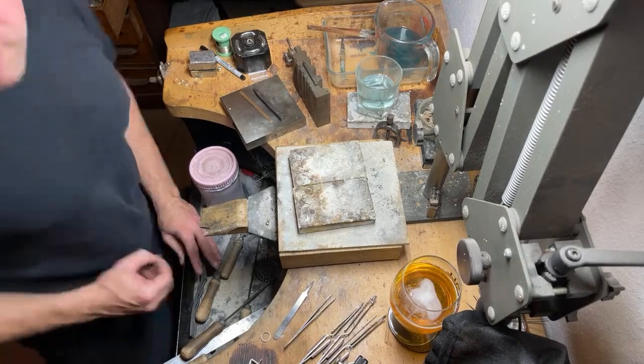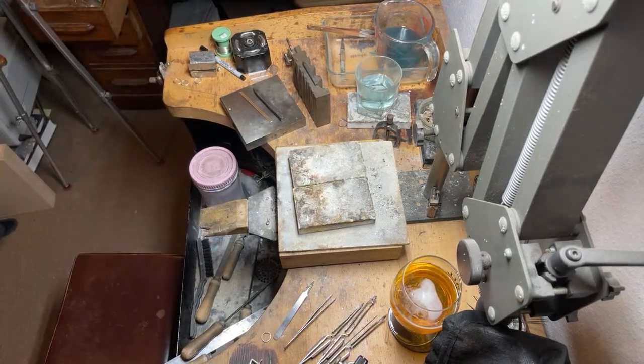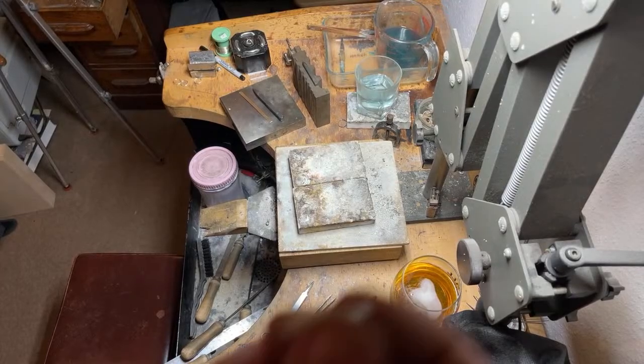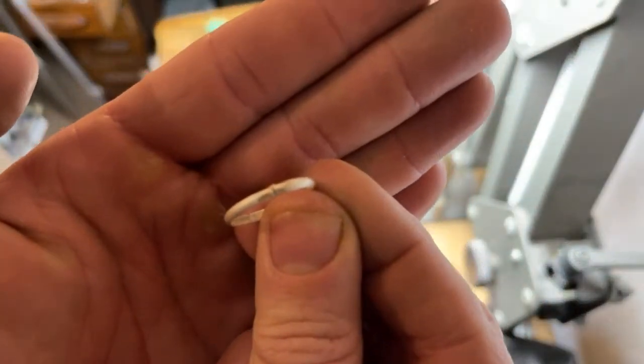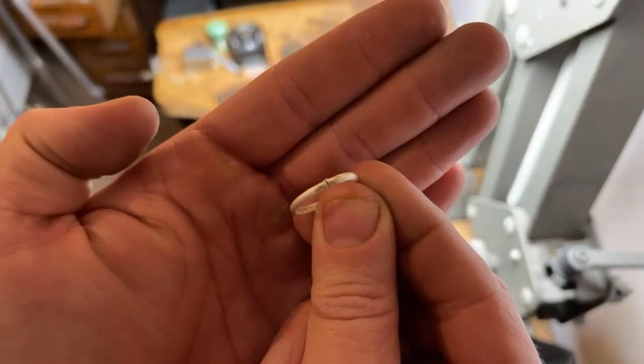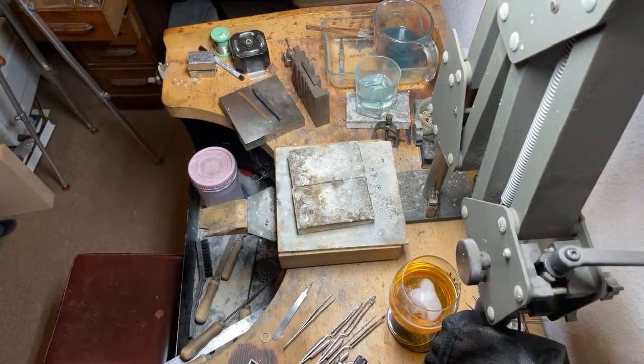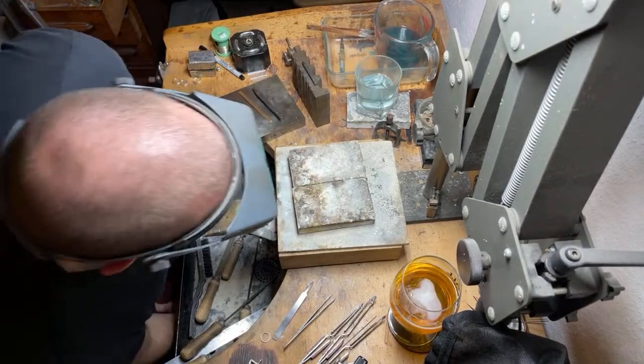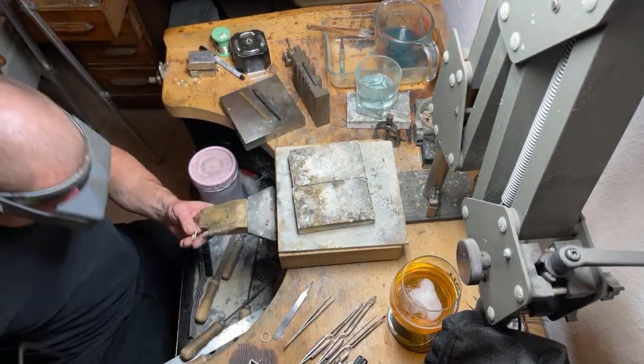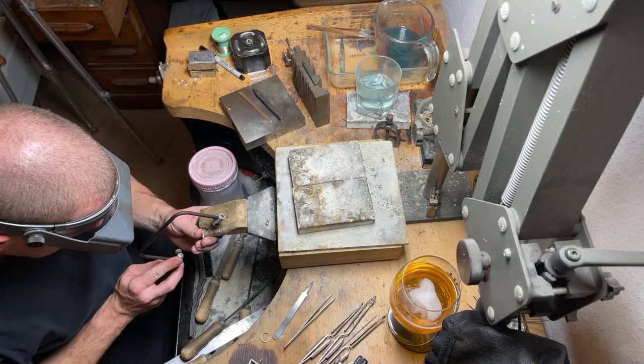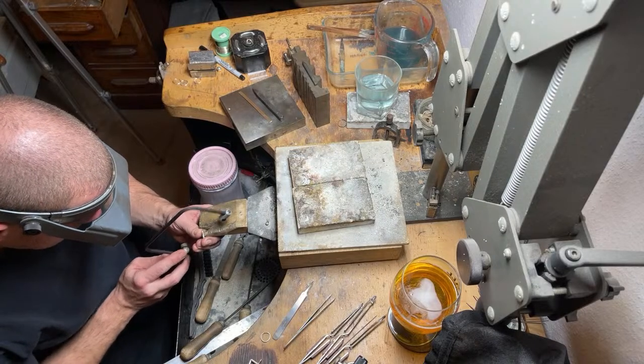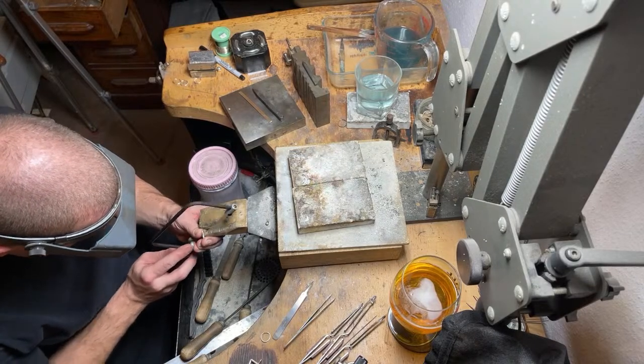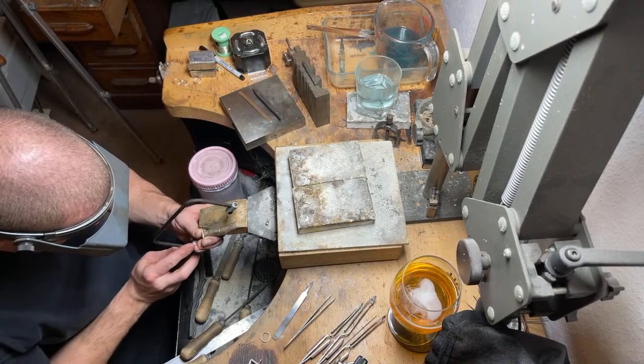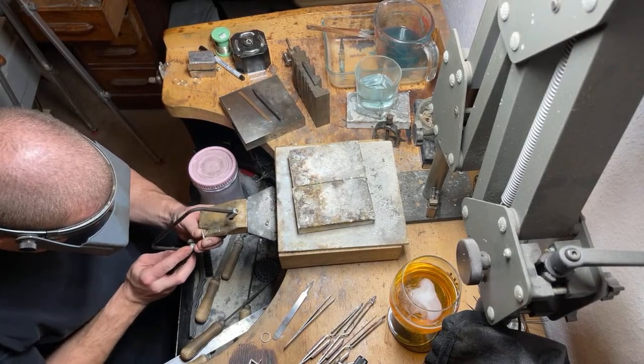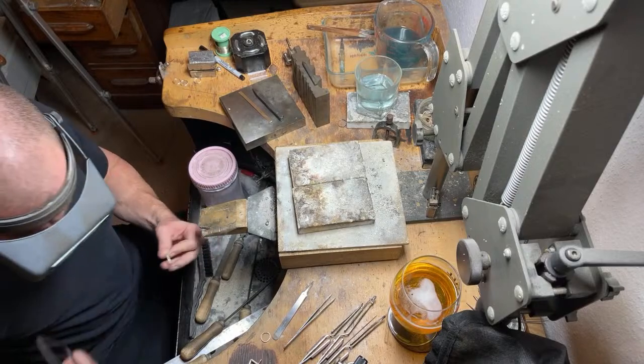I'll show you what I mean. The solder's flowing on both sides, but not bridging the gap. It's a really strange phenomenon. Look at that. Have you ever seen solder do that before? And that was a really close fitting joint when I went to solder. It's bizarre. It's not so bad with the gold wire. You still have to clean the surface off. Sterling silver is the worst.